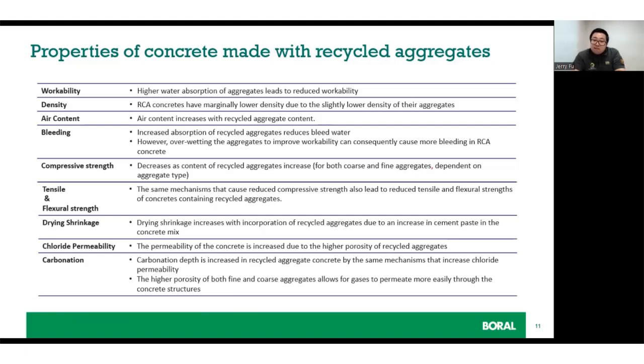Therefore, a good mix design and preparation of these aggregates are needed to produce high quality concrete. As we have mentioned, recycled aggregates have lower density and high porosity. These can lead to faster ion ingression. The high porosity of both the fine and coarse recycled aggregates allows gases to permeate more easily through the concrete internal matrix. So I'm going to skip the rest of these issues that are listed on the slides due to the time limit.